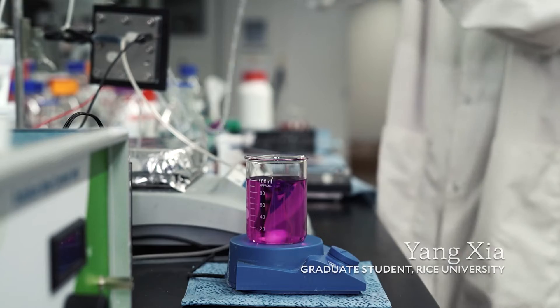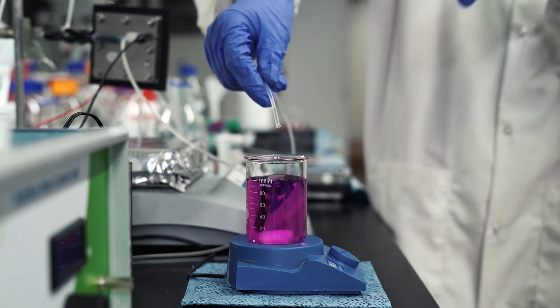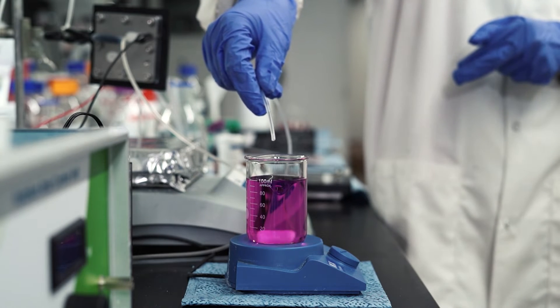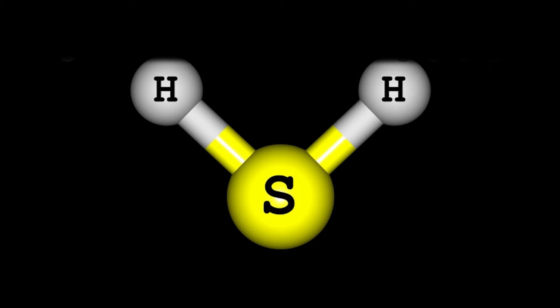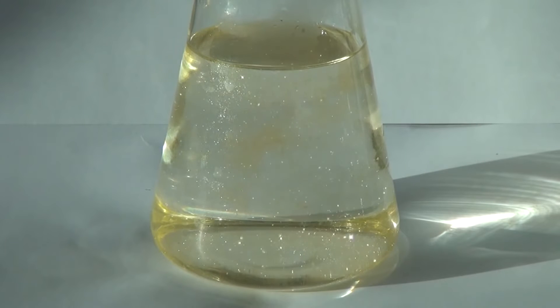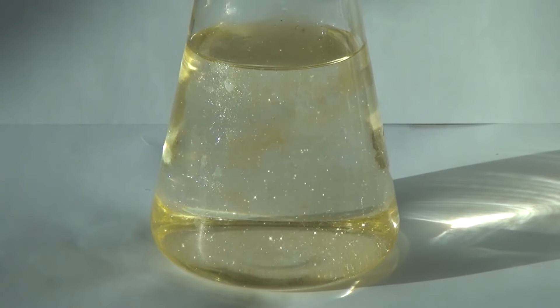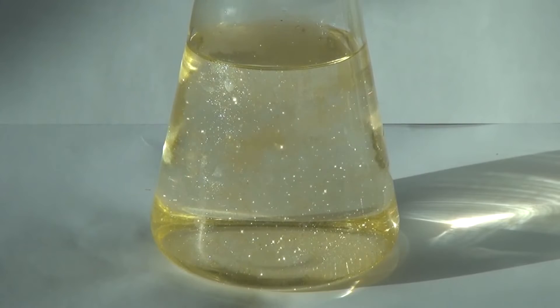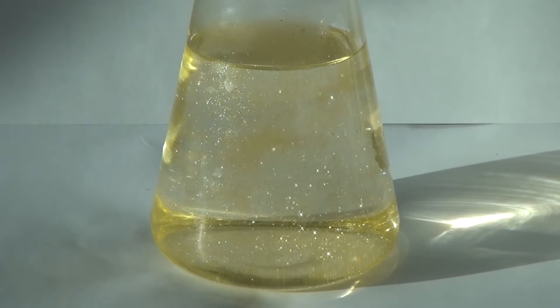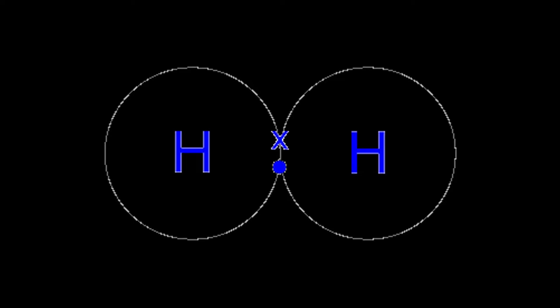In addition, this doesn't use a lot of energy, since the one-step process gets all its energy from light. Each molecule of hydrogen sulfide gas contains a pair of hydrogen atoms and one atom of sulfur. The new process uses a nano-engineered silicon dioxide powder catalyst, each one speckled with nanoparticles of gold. These gold particles respond strongly to a specific wavelength of visible light, shooting out short-lived electrons known as hot carriers, which carry enough energy to split the hydrogen sulfide molecules efficiently into hydrogen and sulfur.